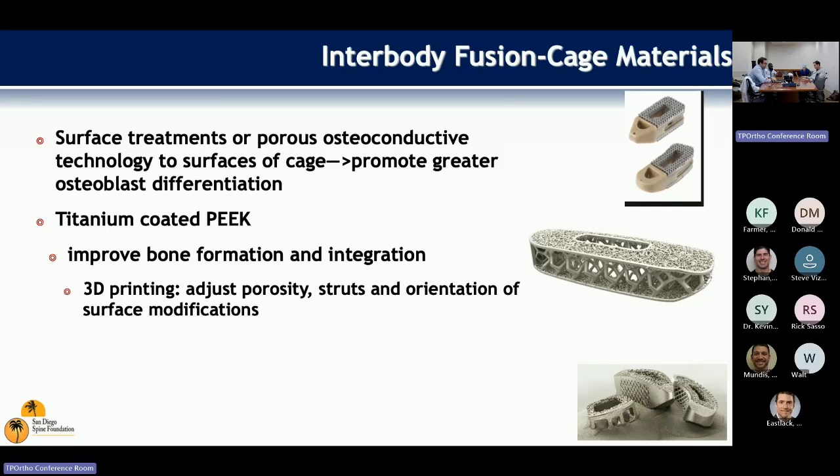And then titanium-coated PEEK, which is a newer technology and something that we do see here from time to time. It aims to blend the radiolucency of PEEK with the osseointegration of titanium. There still are some concerns about the coating delaminating off of the PEEK and wear debris, but overall, it's a pretty low concern. And 3D printed titanium and hybrid constructs attempt to solve the issues: titanium maybe being too stiff for osteoporotic bone, and PEEK maybe not having as much bioavailability or biocompatibility as titanium. So this is sort of what brought titanium-coated PEEK to the forefront.